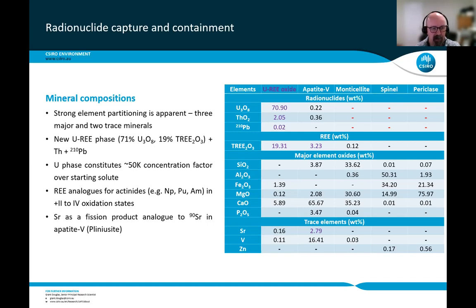The only other thing I'd say as well, the rare earths are important when you look at them as analogues for actinides, the neptunium, plutonium, and the like, in +2 to +4 oxidation states. So in the uranium rare earth oxide, we've got the uranium, we've got the daughter radionuclides, and then we've potentially also got a whole lot of actinides that we can accommodate into the structure. But then in the apatite, we also mop up most of the strontium, and by implication strontium-90. The monticellite, the spinel, and the periclase, if you just look at the top of that diagram, pretty much contain no uranium, no thorium, no lead-210, and only a tiny amount of rare earths. So all of the other major phases, which constitute greater than 99.9% of the sample, are effectively clean. So we've concentrated everything into 0.1% of this sample.